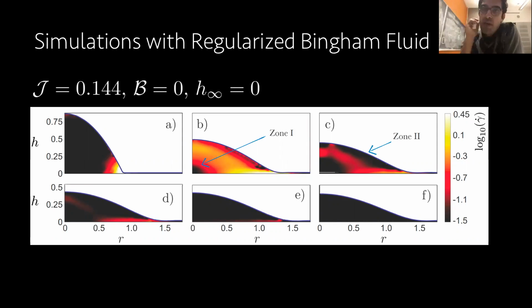So with such a method, we can also look into more of the anatomy of the flow. What you will see is that, of course, you have high curvature at the contact line that drives the flow. And then at the center, something grows that looks like a static plug. There's a stagnation point there, so it's not surprising that a static plug forms there. As time goes on, there is another low deformation zone growing close to the surface, which looks like a rotating, co-moving plug region at the surface. What is more important for our application is that at some time, like in the lubrication case, everything inside the droplet has stress falling below the yield stress, and the droplet stops spreading. And that's my final radius, okay?